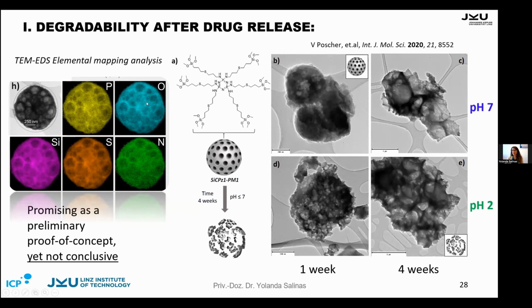This foam-like particle contains specific cavities that could be loaded or linked with some specific cancer drugs. That was very promising and a proof of concept, yet not conclusive, because it allowed us to observe the possibility, since for the first time we used polyphosphazenes and silica together. This material was developed by my PhD student, Vanessa Poscher. And after many, many trials, we observed that the material was able to degrade even at pH 7 after 4 weeks.